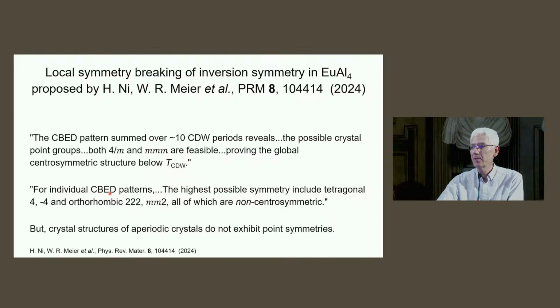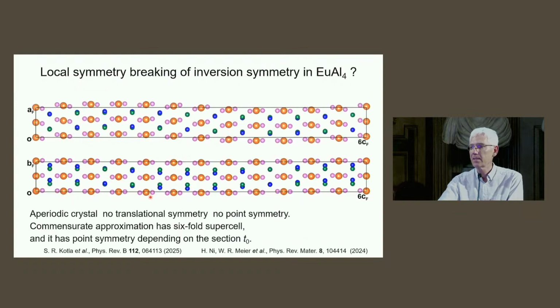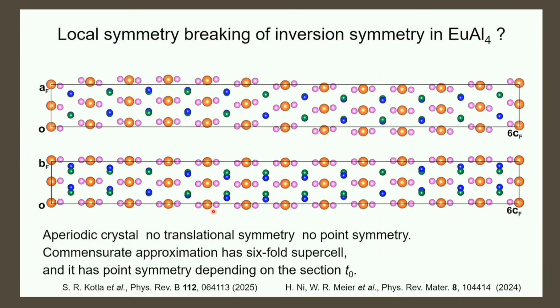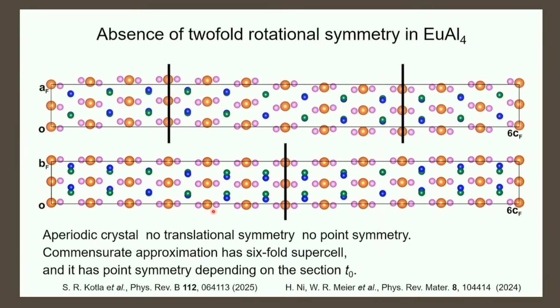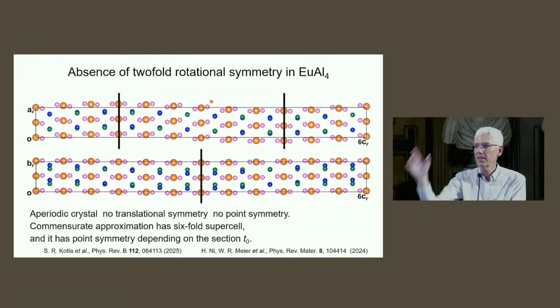Nevertheless, in convergent beam electron diffraction, you see the point symmetry, and they came up with non-centrosymmetric, so we tried non-centrosymmetric. First, this picture. This is my would-be twofold rotations, and it's maybe not all that easy to see. Here the green is on top and the blue on the back. Here the blue is on top and the green is on the back, so that seems to match with a twofold rotation about this axis, but there are other parts.